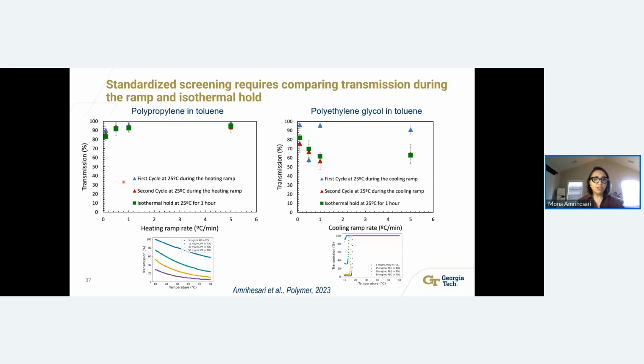On the right, again, you will see the polyethylene glycol in toluene, and we compare the first cycle and second cycles again with the isothermal hold. What we observe here is that the first cycle is not matching the changes during the second cycle and isothermal hold. That is because the polymers are, as I mentioned, being a large molecule and they are commercially bought, they store a little bit of thermal history.